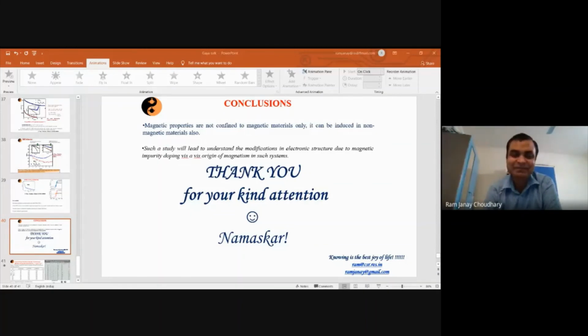In magnetic oxide materials, is there a possibility of direct exchange interaction? Certainly, there are possibilities. As I said earlier, it depends on the crystal structure. If the crystal structure of your magnetic oxide material is such that the magnetic ions are closer to each other rather than via oxygen, then all these interactions depend hugely on the distance between the two magnetic ions. So if the two magnetic ions are close to each other, there is always a possibility of direct exchange interaction. Having said that, you cannot always rule out direct exchange interaction.